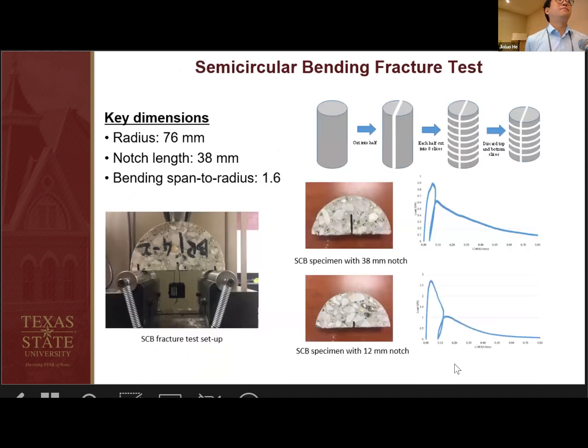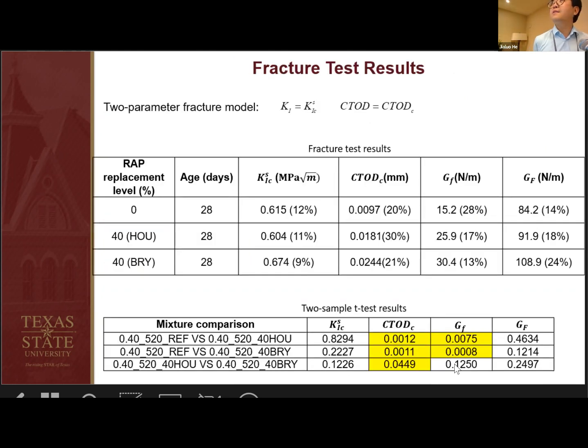In addition to those conventional tests, I also developed a fracture mechanics-based test to evaluate the fracture properties of RAP concrete. I developed a semicircular bending fracture test to determine the two primary fracture model parameters based on Dr. Shah's fracture mechanics theory. I want to skip a lot of details because we only have 15 minutes.